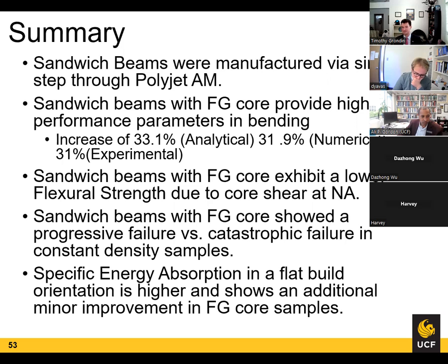The Stratasys J55 was capable of creating repeatable sample qualities with similar defect densities and microstructures. The hypothesis was proven through FEM, and then again proven through experimental data. And we had a functionally graded design that ended up having a higher stiffness to weight ratio. The numbers are in agreement: you can see an increase analytically of 33.1%, 31.9% numerically, and then 31% flat for our experimental results. So the data is in agreement.